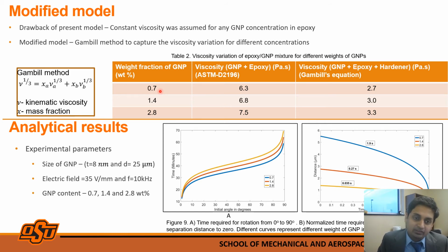So adding all these up, we end up with analytical results for the modified model. In this picture, you can see the time required for a single graphene nanoplatelet to align from 0 degrees to 90 degrees for three different weight fractions. These results are based on the formulas which you saw earlier. Similarly, the translation time is also depicted in figure 9 part B, where yellow is 2.8 weight%, red is 1.4 and blue is 0.7.